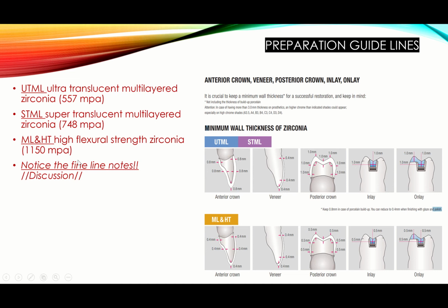And I want you to notice certain things. If it's in your area that you don't use these zirconia blocks that much, I want you to notice a few things. First of all, look at the naming: multi-layered and high translucent, high flexural strength zirconia. When you hear high translucent or multi-layered, you would think that this is a very high translucent zirconia and that it has reduced mechanical properties, because higher translucency pretty much means lower strength. But here it says flexural strength zirconia is 1150, almost 1200 megapascal of strength. So if this is translucent zirconia, then what is this? A super translucent multilayer zirconia, and then an ultra translucent multilayer zirconia.